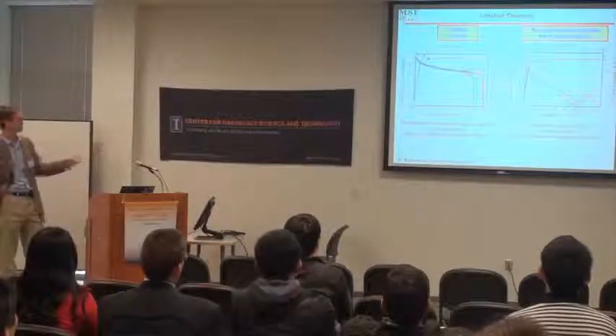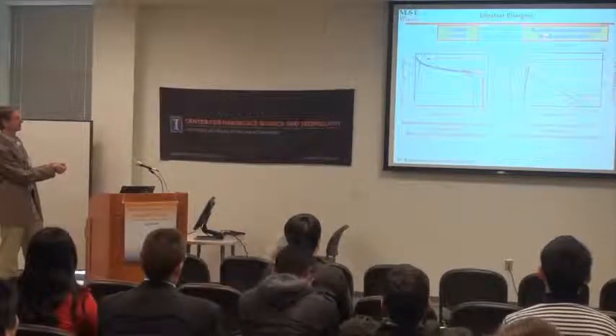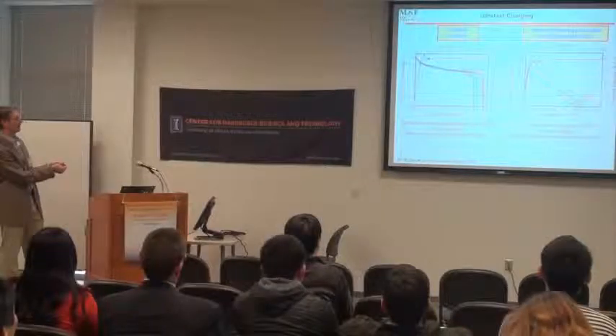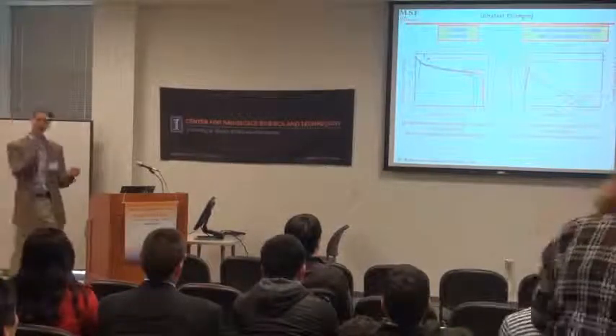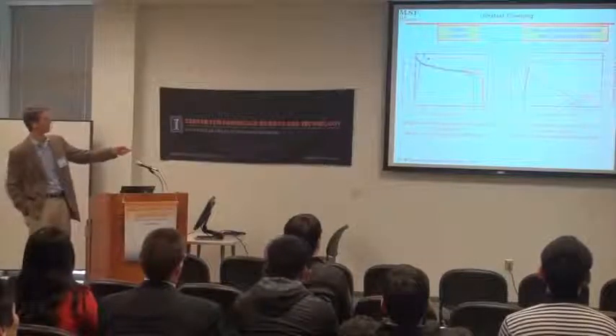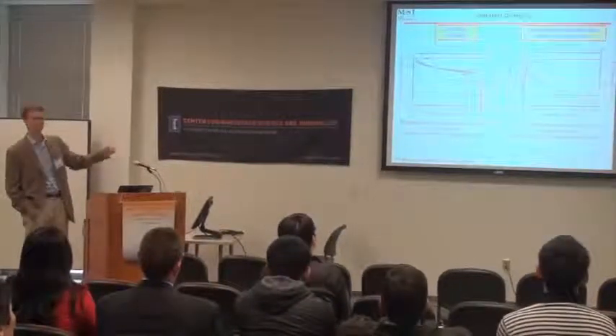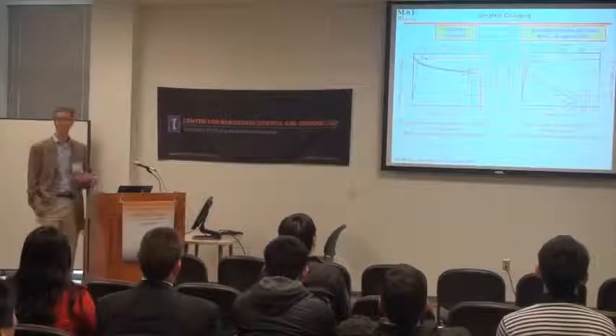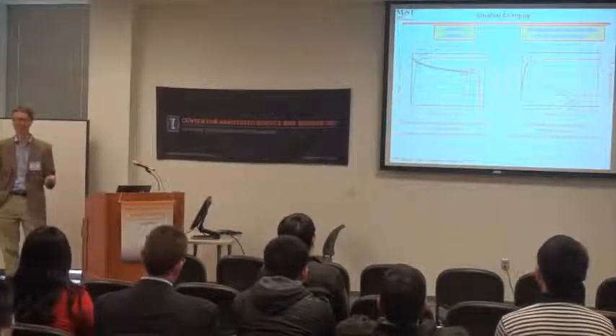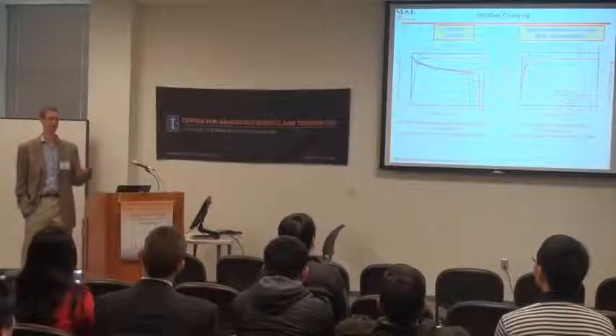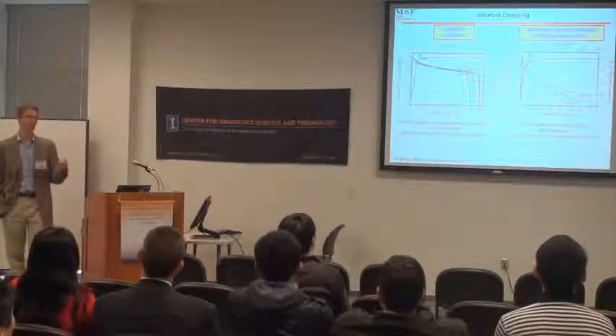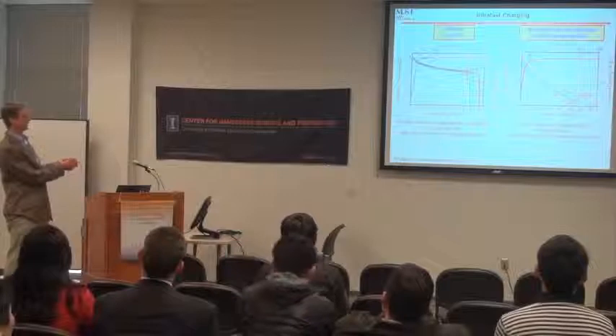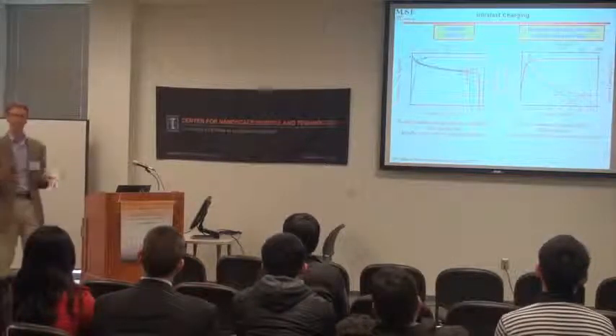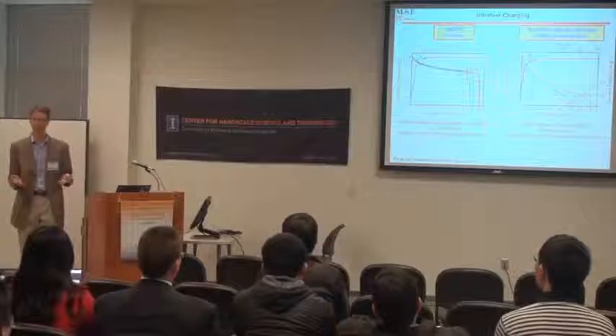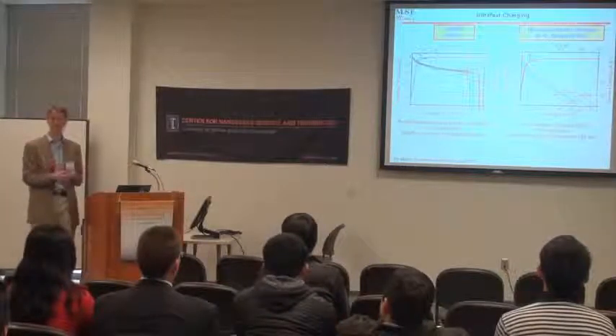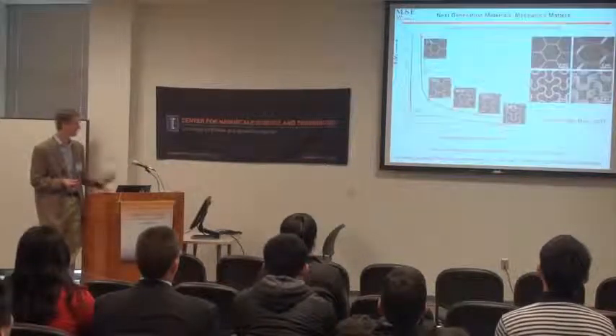This is, again, a half cell. We'll ignore that. This is a real battery now, using our cathode with a conventional graphite anode. It turns out the anodes are a little bit faster. What I'd like you to see here are charge curves. In 60 seconds, the battery is 80% charged. In 2 minutes, 120 seconds, it's about 90% charged. And after about 10 minutes, it's fully charged. The discharge follows the same characteristics. You can get about 80% of the power out of the battery in about 1 minute. That's really a design space that has not previously been available.